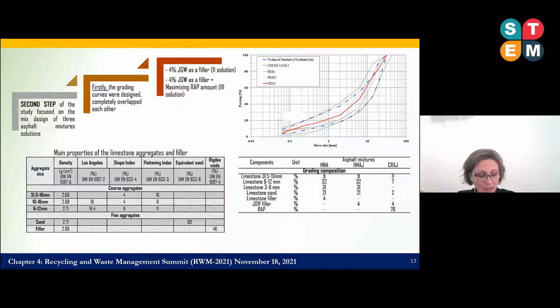And we designed the second solution that included the jet grouting waste as a filler in complete substitution of limestone filler. In particular, for the cold recycling asphalt mixtures, we used 4% of jet grouting waste as a filler and a huge amount of reclaimed asphalt pavement.